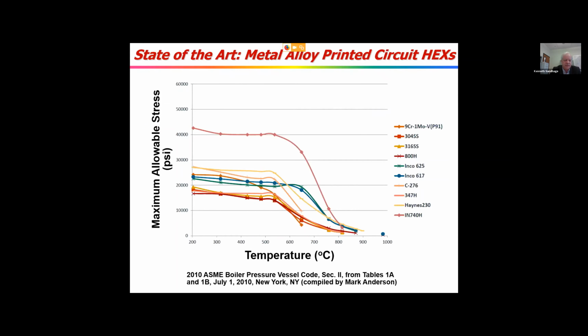And I have to say that these two materials, the metal alloys and ZrC-tungsten, fail in different ways. ZrC-tungsten fails by fracture as opposed to predominantly creep rupture for metal alloys. But the point is, the failure strengths are dramatically different. For the metal alloys, as I mentioned, you're looking at 5,000 PSI or so at 800 C. Our material is on the order of 87,000, way off the chart here. And so we think it has strong potential for that reason from its mechanical perspective.